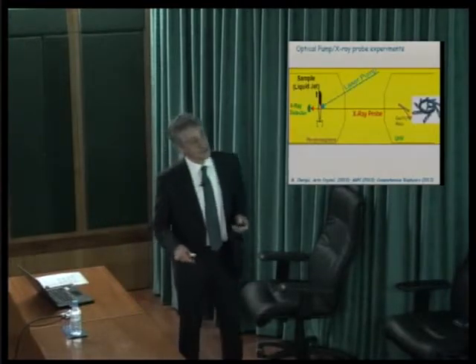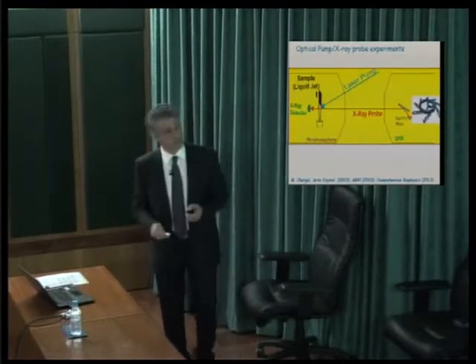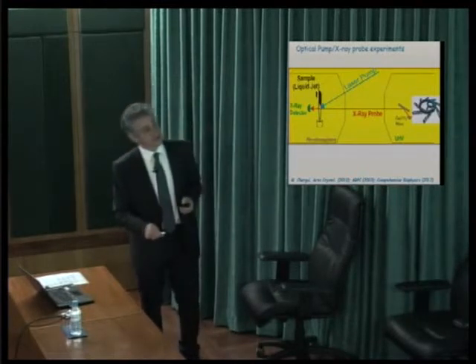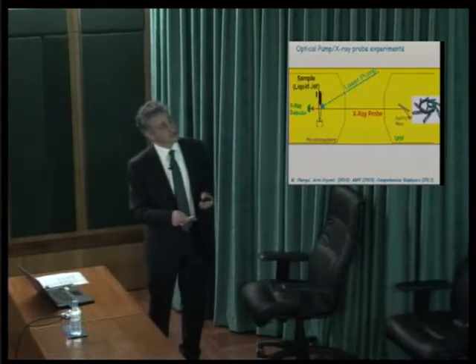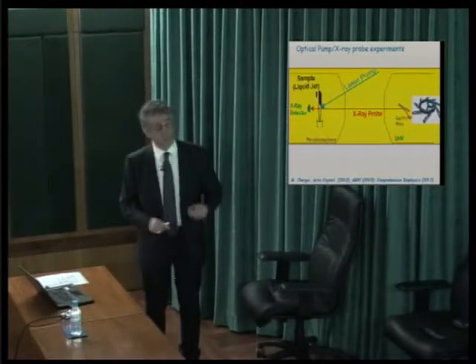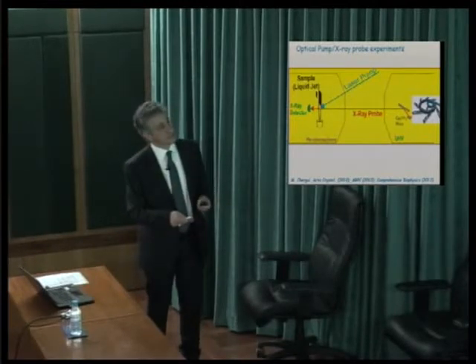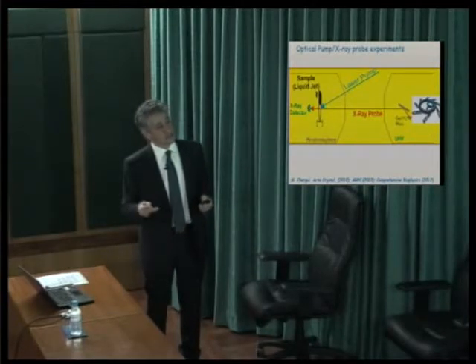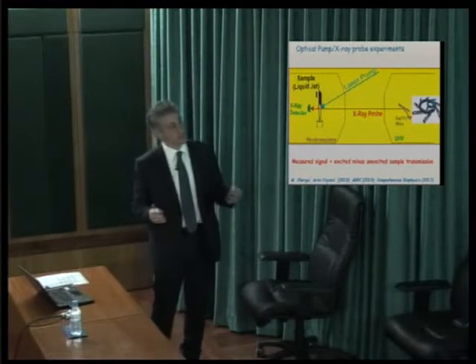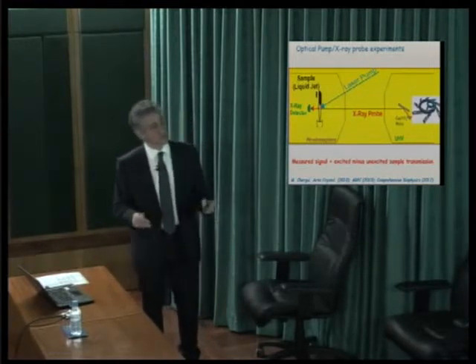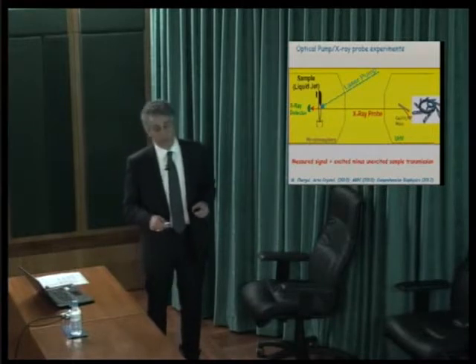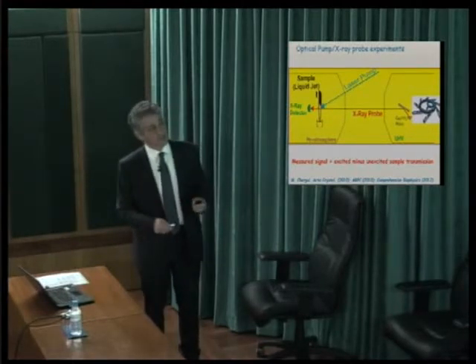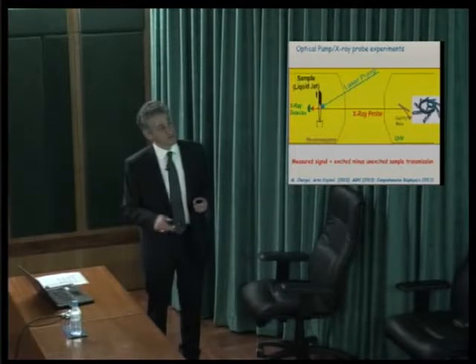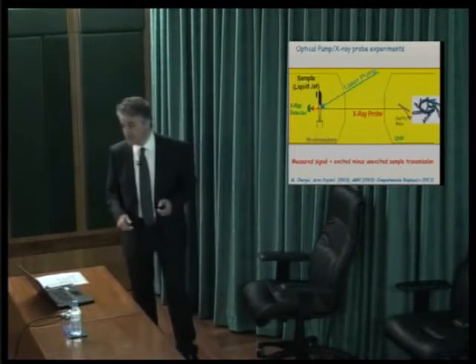OK, the way we do the experiment is like in all the pump probe experiments. You go to a synchrotron, you excite your sample, it could be a recirculating jet, with a short laser pulse, and then you probe it with a time-delayed probe pulse. And we take basically the difference between the excited minus unexcited sample transmission, and that's basically the observable. That's more or less the same as you do with all pump probe techniques, except that here the probe pulse is the X-ray pulse.